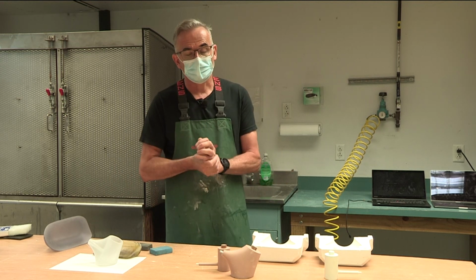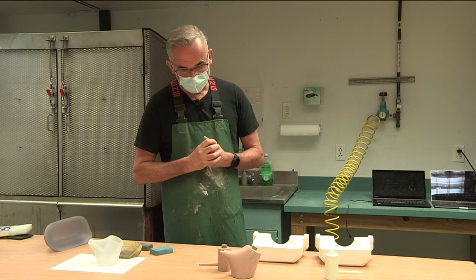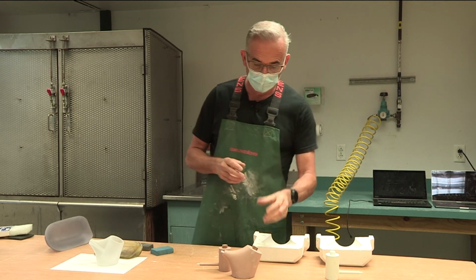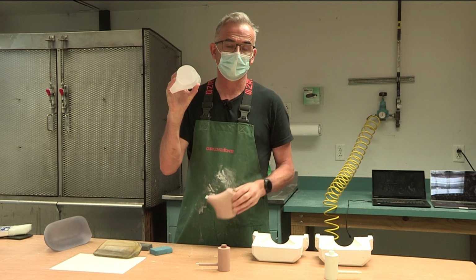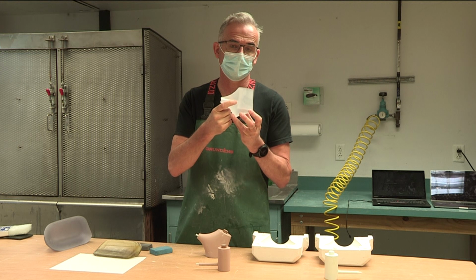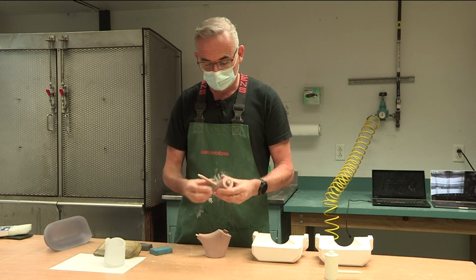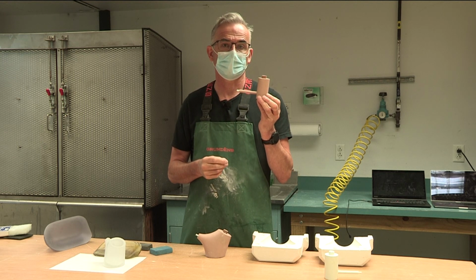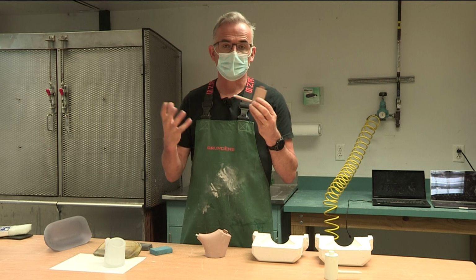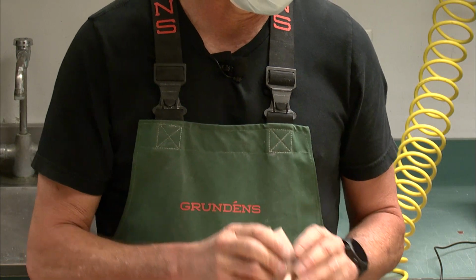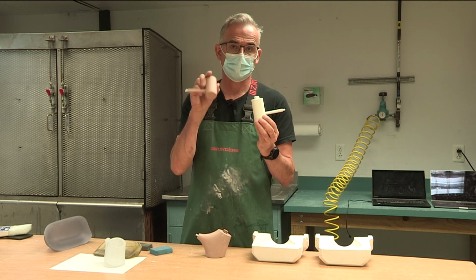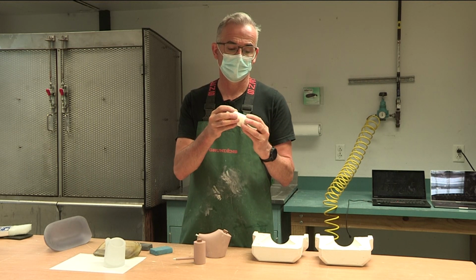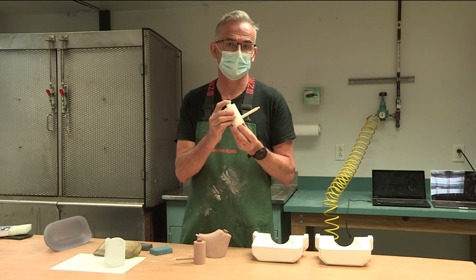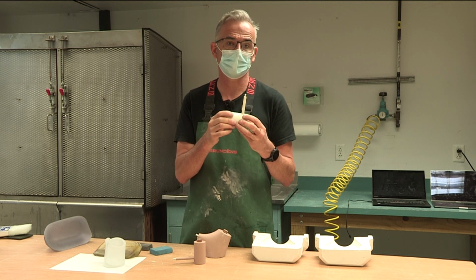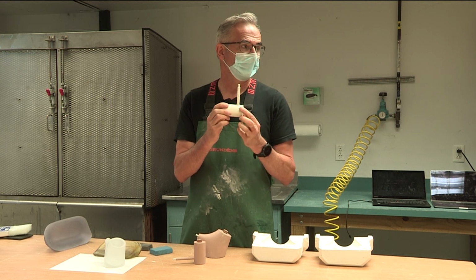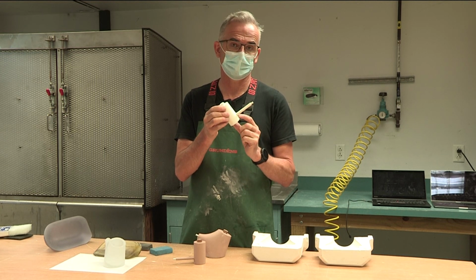That casting project that you just saw was quite complicated, because what they were trying to do is to make this particular form with the hollow core in it, and it's quite a delicate little hollow core in the middle. So what we did is we asked the designer to make the interior as a positive. It's very similar to the way that I make my own work. We made the negative as a positive. So that's this form here. We made a retrievable mold out of that, and then we cast this in a high quality, commercially made casting investment material. We experimented with a lot of different materials, but the only one that held up was the one that could hold this little join here.